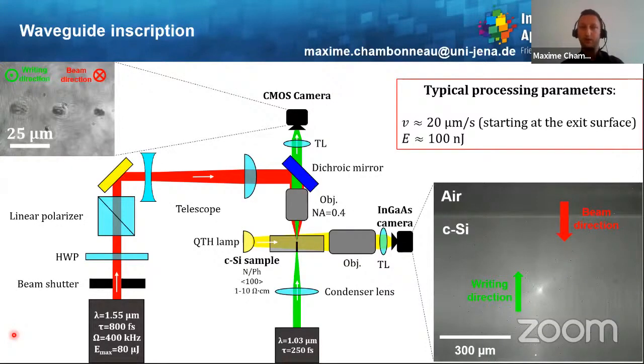So for inscribing waveguides inside silicon, we have developed the following experimental arrangement, relying on pulses at 1.55 micron wavelength, 800 femtosecond pulse duration, and a few tens of microjoule in terms of maximum input pulse energy. Then we adjust the input pulse energy by means of a half wave plate and a polarizer. So this is controlled optically. Similarly, the beam size is controlled optically by means of telescopes, Galilean telescopes in that case, before the beam is focused to the wafer, so the silicon sample, by means of an objective lens.